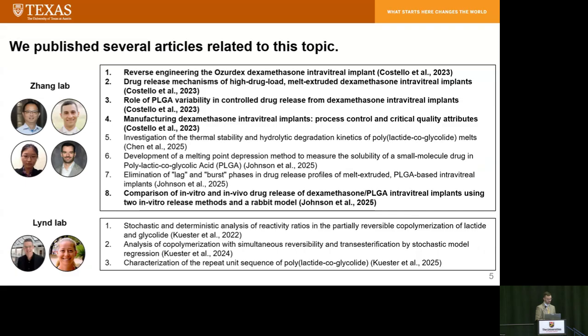So our strategy for the reverse engineering of Ozurdex had 3 parts. Part 1 was to understand the formulation, which is basically a monolithic cylinder with dexamethasone crystals dispersed in a PLGA matrix. Step 2 of our reverse engineering project was to master the implant manufacturing process, which is melt extrusion. And then part 3 was to understand the drug release mechanism of these implants and relate what we understood about the release mechanism back to the formulation and back to the manufacturing process.